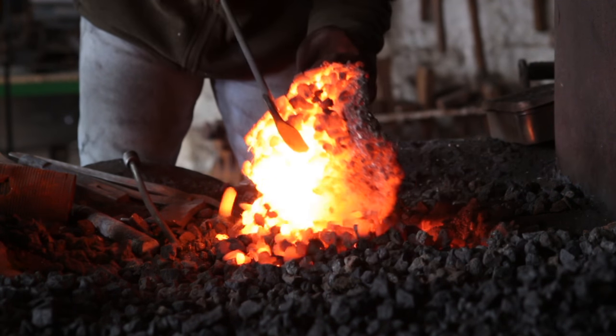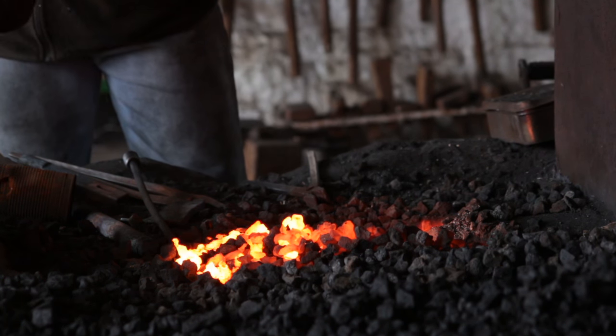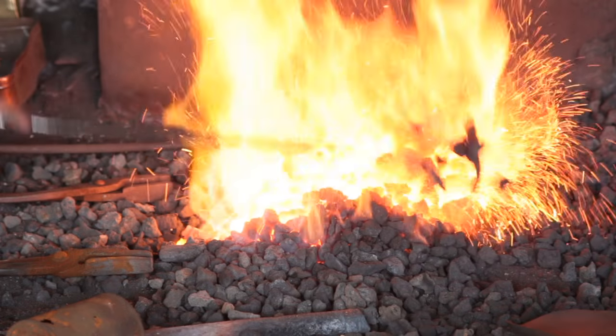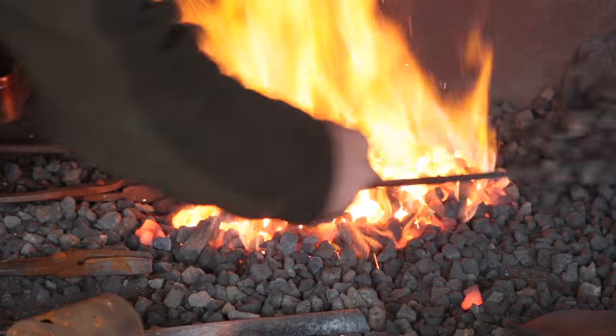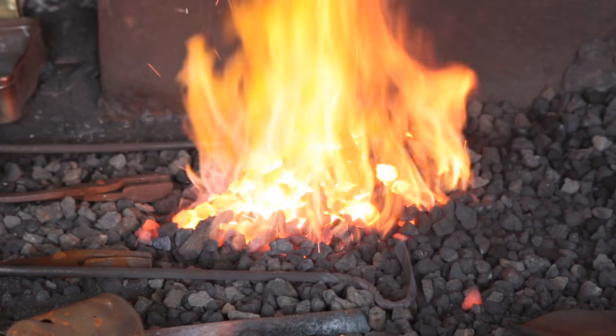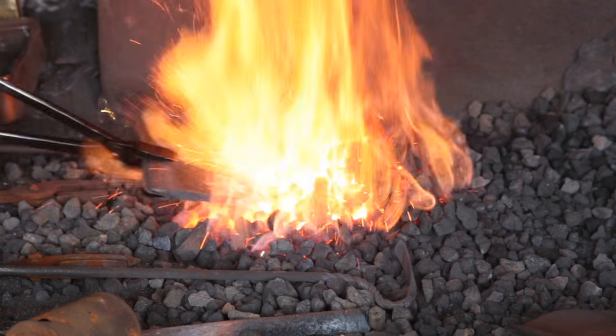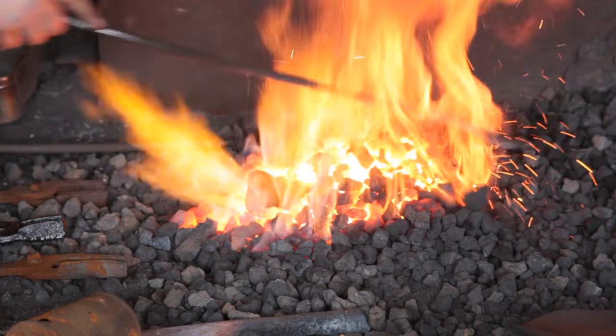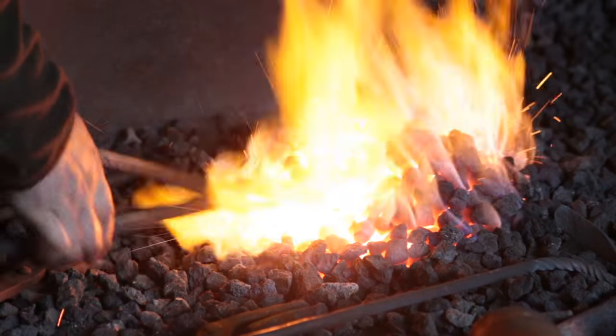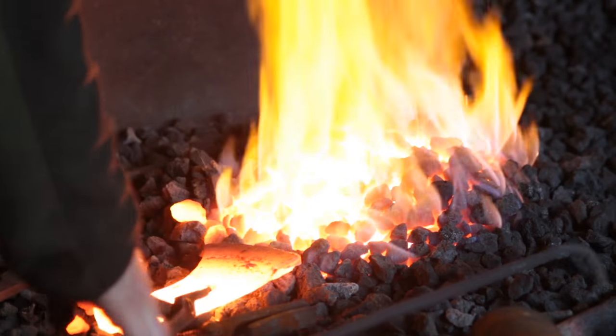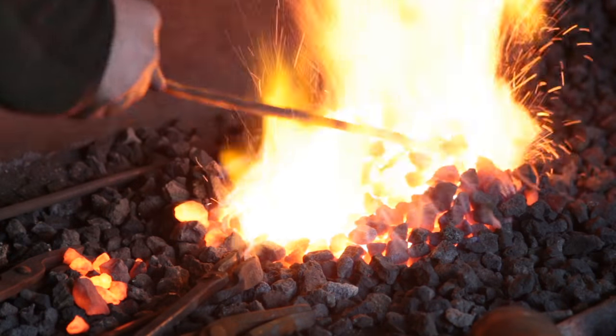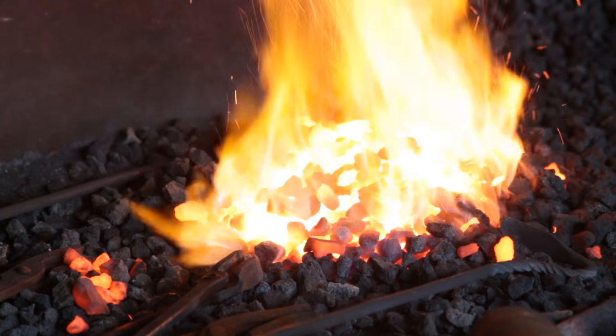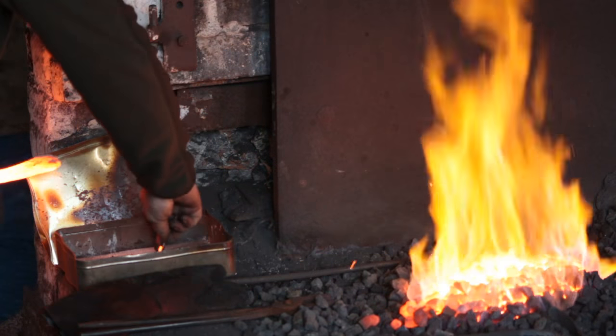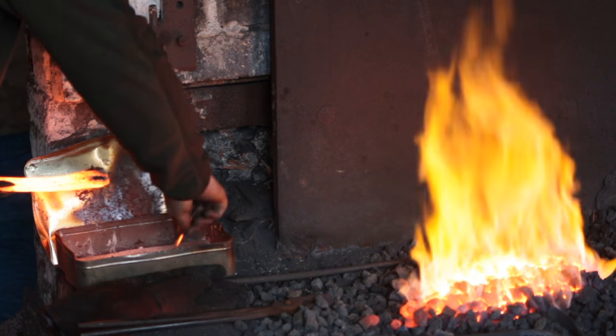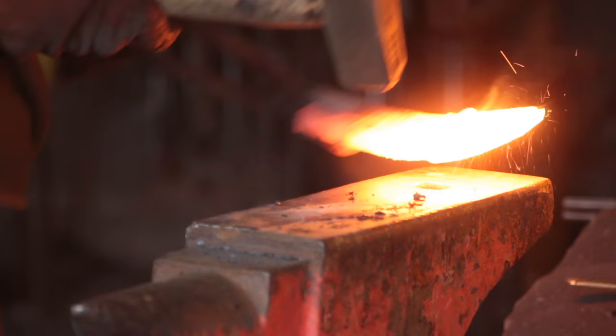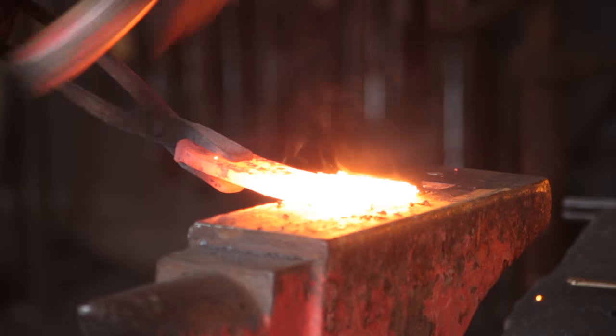So the reason I'm cleaning out the fire is because it's reducing the oxidizing layer of the fire. So I want to pile up the fire nice and high to have a nice wide neutral layer, which will reduce the burning risk to the steel. So I'm sticking the axe in there, eye first, and then I will turn it round and stick the bit in. And that just means that the whole thing is hot and it's not going to suck out the heat from the welding area. So stick a bit of flux on the carbon steel and go for a weld.